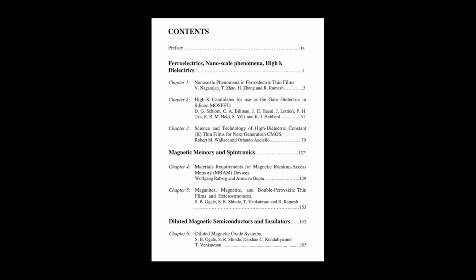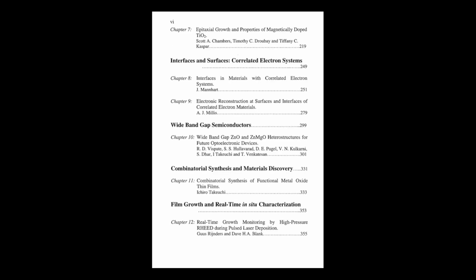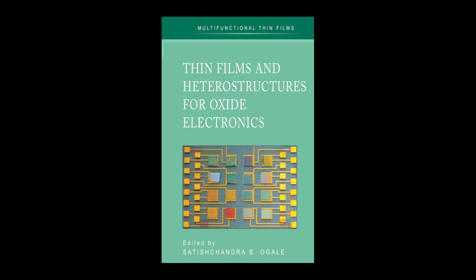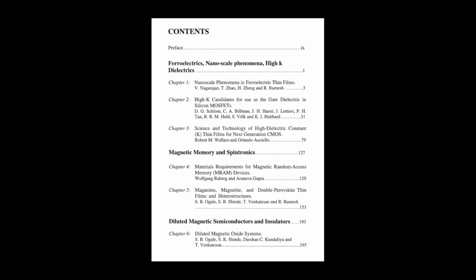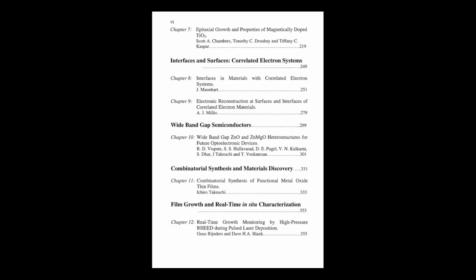HfO2, that's the one Intel eventually used, right? Hafnium-based. Yes, HfO2 became the industry workhorse. But the calculations, interestingly, pointed even more strongly towards certain complex perovskite structures. And the absolute standout, according to this predictive method, was lanthanum aluminate, LaAlO3. LaAlO3 looked almost perfect on paper. The calculations predicted a high K, and experiments confirmed it, measured values around 24-25.